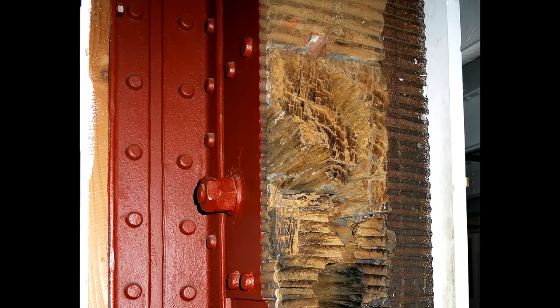It's not going to provide any resistance to our 32-pound equivalent shot, because it's no longer there. It's not even going to provide the limited resistance to our anti-personnel shot simulated by the gel blaster rounds, which the cardboard, the wood analog, still would, because it would be, you know, just generally there with a few small holes in it, whereas this is completely gone and doesn't even protect you from an angry person with a pistol. You can see how with a brittle failure, the cracks have propagated. They've actually joined up with a previous impact point, and that's been the end of that. So was there a solution to this conundrum?